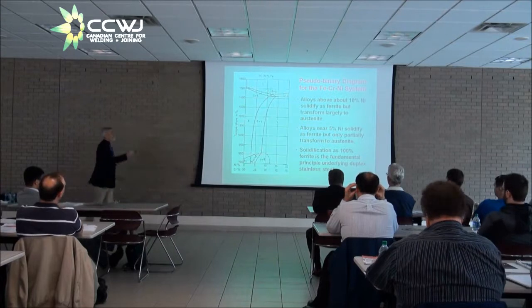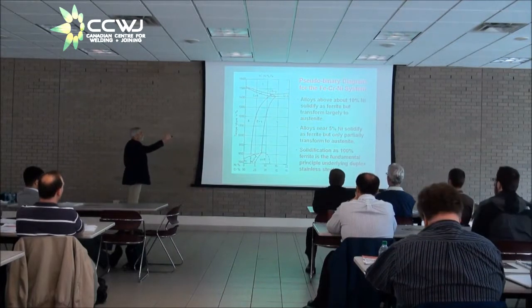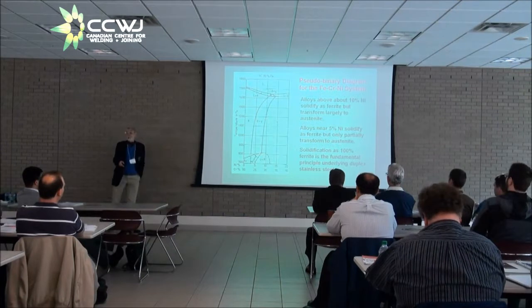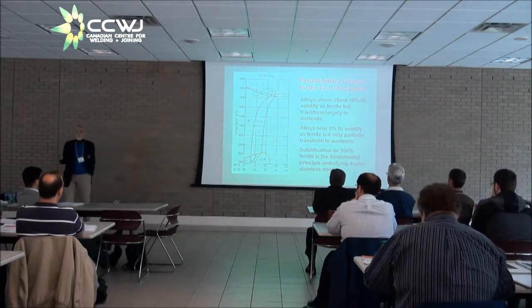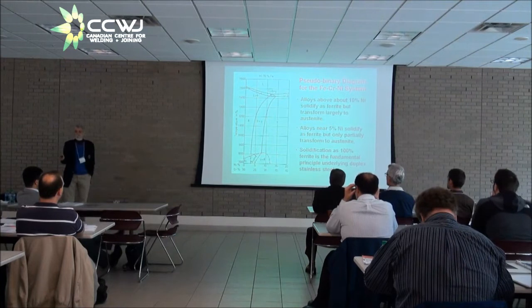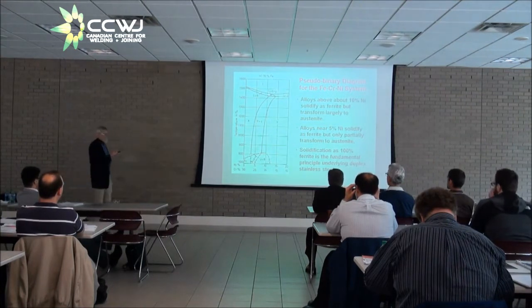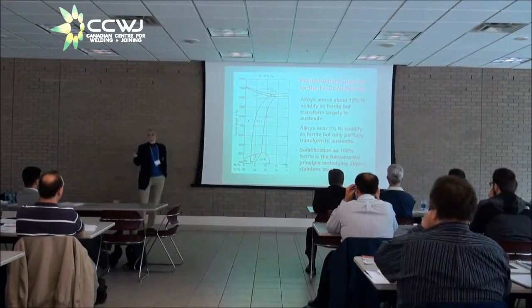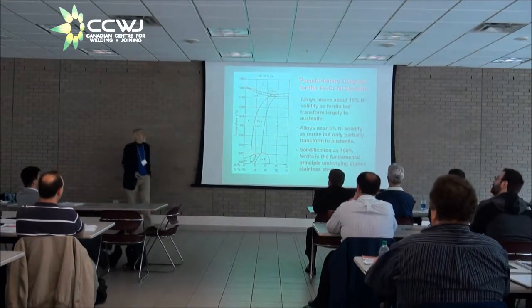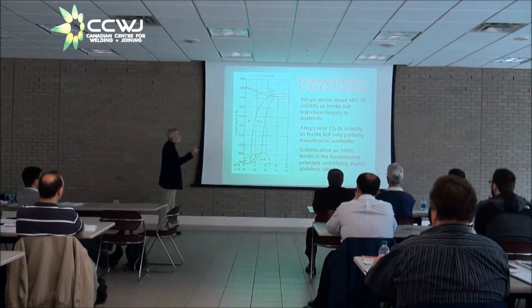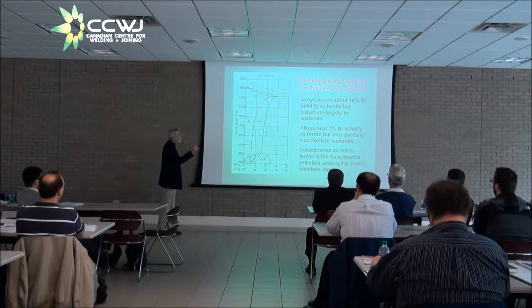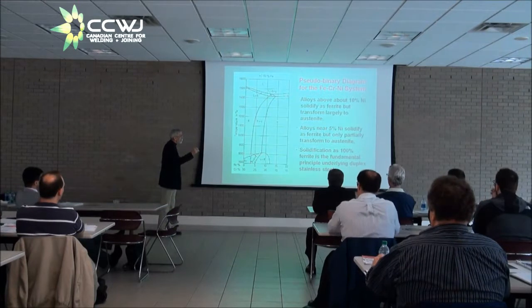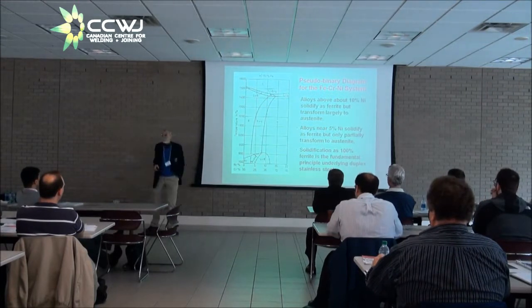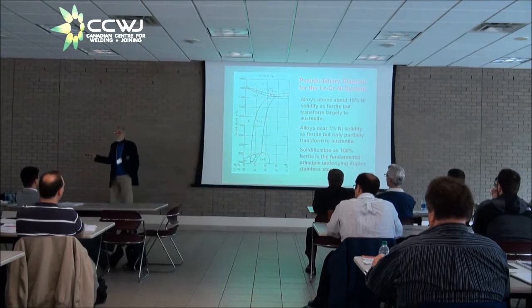And then up at the top here we have liquid, and in the center here we have this triangle. Kotecki triangle, that's called. That's where liquid plus ferrite plus austenite coexist. It's a very small range where all three phases coexist at once. But the important thing about it is that an ordinary austenitic stainless steel, like 304L for example, is going to have a composition very close to the edge of this triangle, so that the metal is going to solidify as liquid going to liquid plus ferrite, going to liquid plus ferrite plus austenite, then into ferrite plus austenite, and eventually down to 100% austenite. That's why your 304 base metal doesn't contain any ferrite.